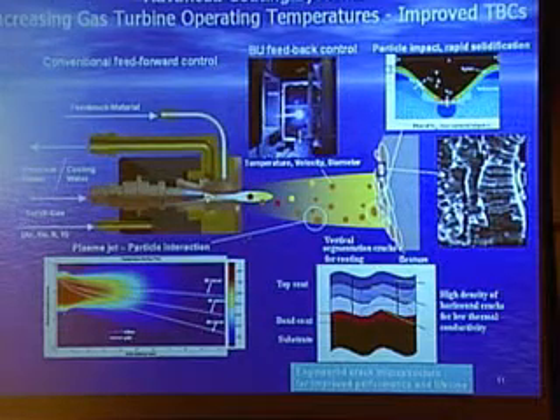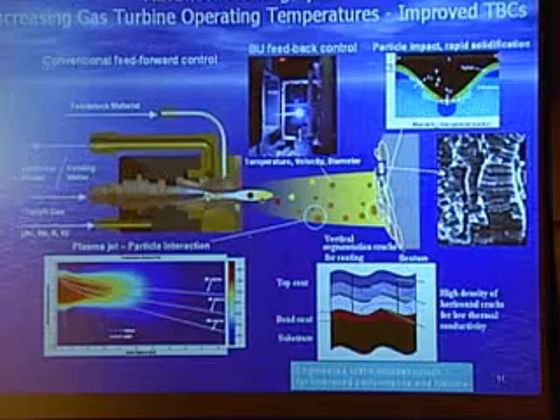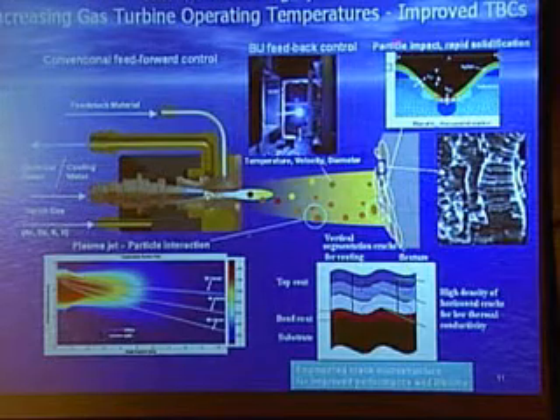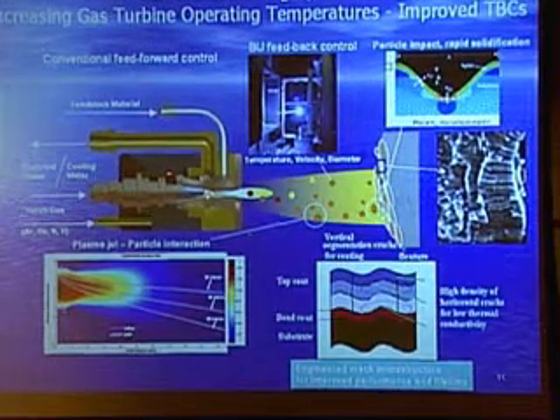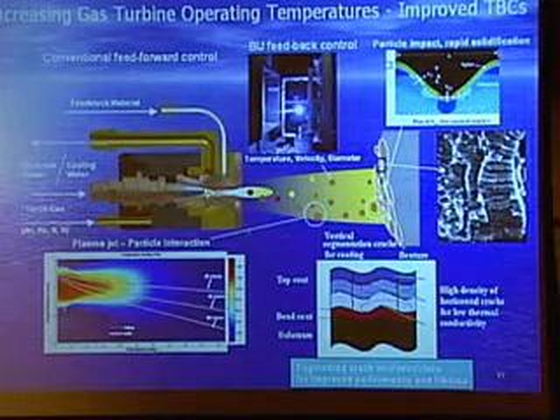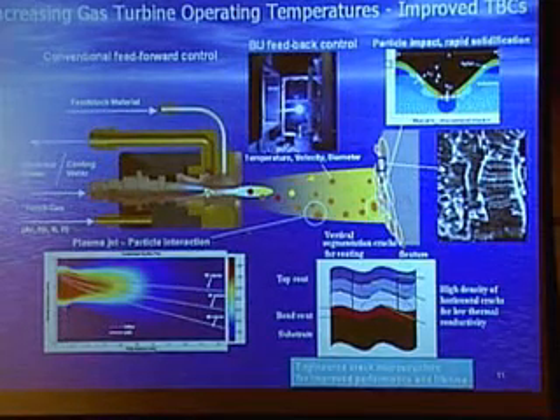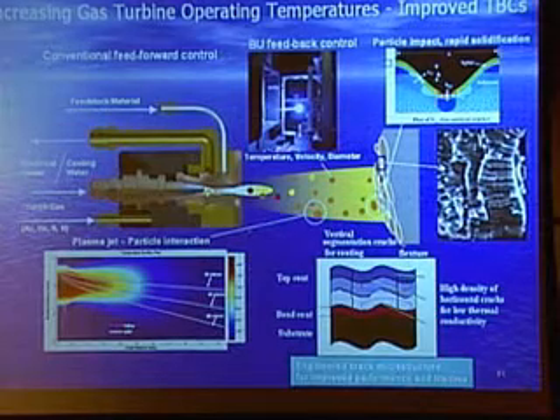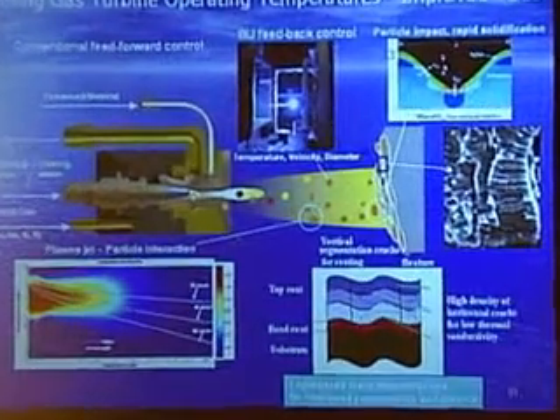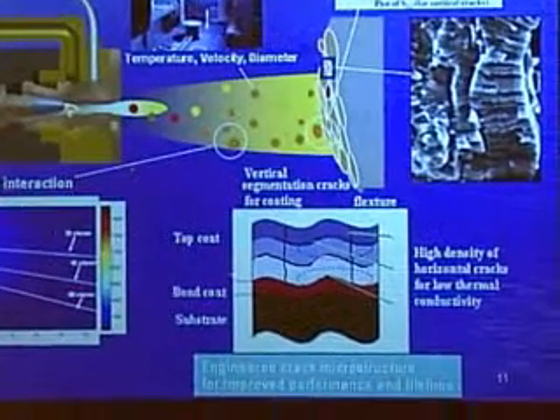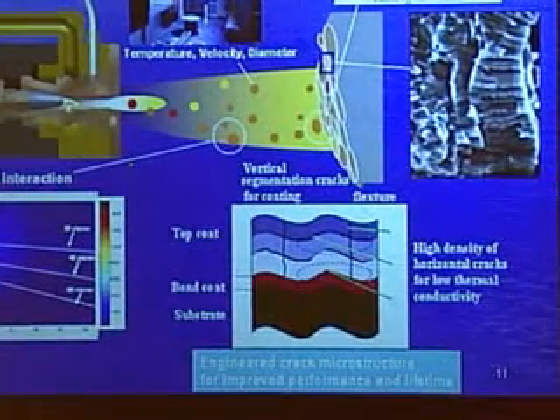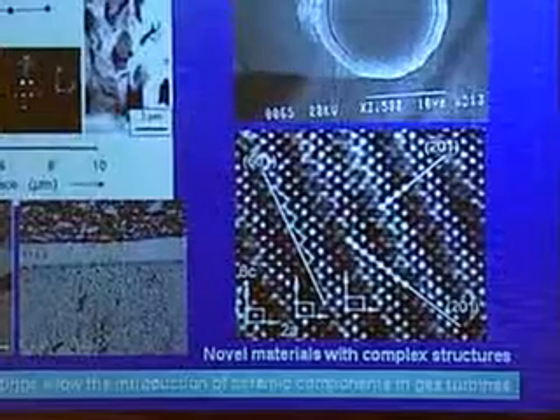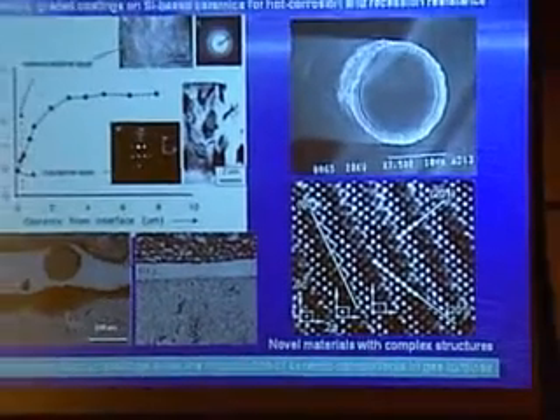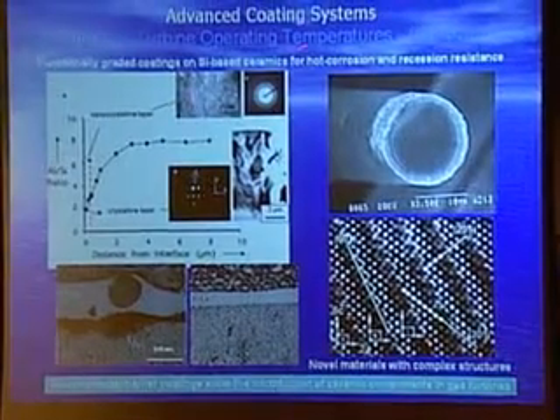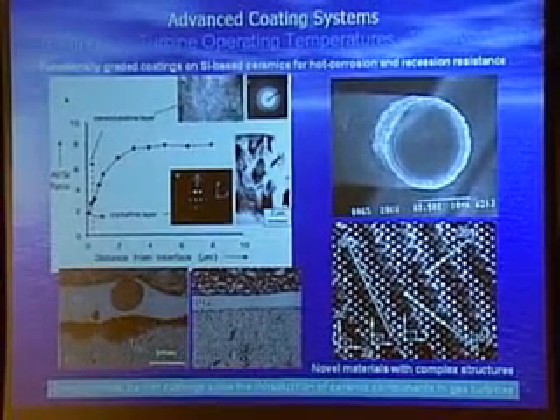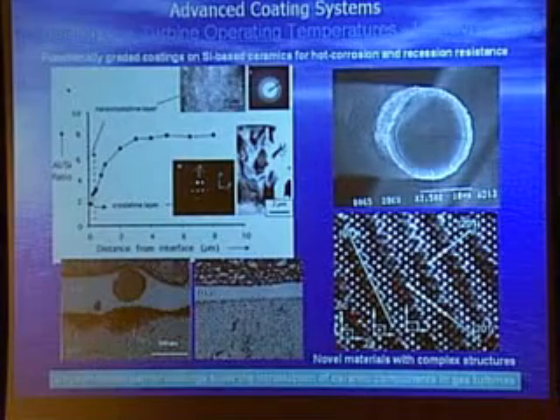And we have developed a real-time feedback control strategy for plasma deposition of thermal barrier coatings. And we control the variables in the plume to engineer the cracks in the coating in order to improve the lifetime and the performance. So as we increase the operating temperature of the gas turbine, the turbines also become susceptible to corrosion, environmental corrosion.